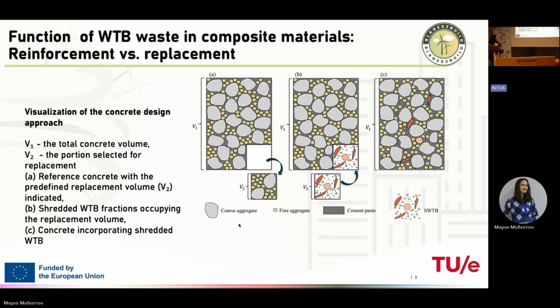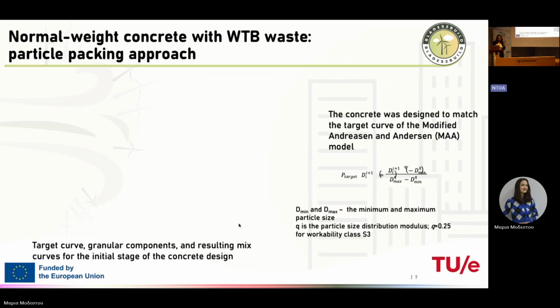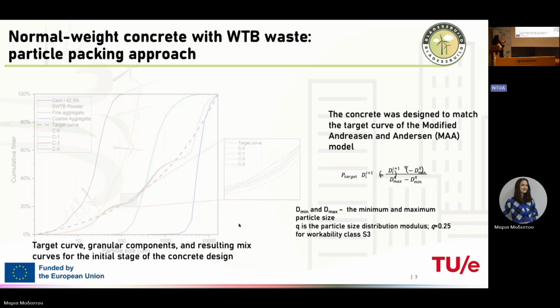And we replace it with shredded wind turbine blades waste. And C, basically, we have concrete with this incorporated wind turbine blades waste. So we try to replace some particles and try to reinforce. So we try to combine two effects on concrete with this waste, since we have fibrous particles, since we have powder, and since we have flakes.